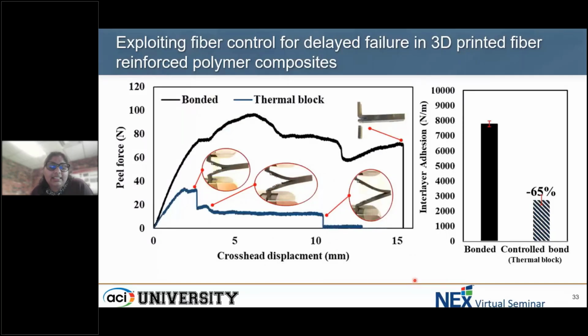This one is a peel test, which is basically a T-flange or a dual cantilever beam that we put into a tensile testing machine, and we are pulling one of the flanges. So that has a 65% interfacial adhesion or interlayer adhesion strength reduction in the controlled bond, which is thermal block, versus the bonded configuration. So clearly from these two interlayer tests that we performed, we were able to distinguish between these two bonds, and because of that reduction, we know that there is transfer of load that is affected.